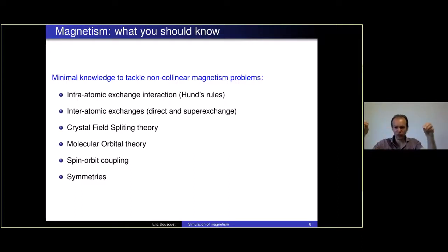And even if you put a ligand in between, like oxygen, fluorine, or nitrogen, and so on, you use what we call the superexchange, which is the magnetic interaction between ion, oxygen, and ion. This magnetic interaction also mostly favors antiferromagnetism. So that's why, from quantum mechanics, we are able to explain why you have many more antiferromagnets than ferromagnetic systems. And on top of that, everything comes from the energy levels of the d orbitals of the transition metals around the atoms, because this is what gives you how much magnetic moment you have on each atom.